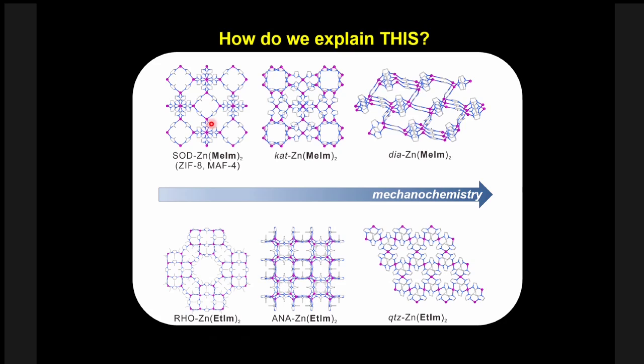But if we have a slightly different organic linker, we replace a methyl group on it with an ethyl group, we again get multiple steps in the reaction, but now frameworks look completely different. This one has a structure which is known as zeolite rho. This one has a topology of analcime. This one quartz. So why does this happen in the first place? Are these some kind of strange high energy phases we are making? Are we making new chemistry, or is this something we would expect?